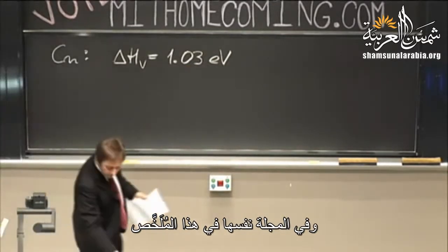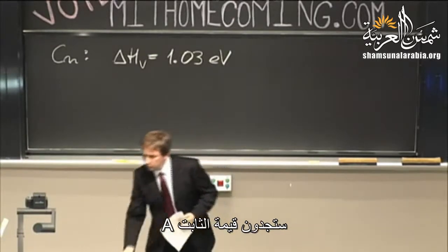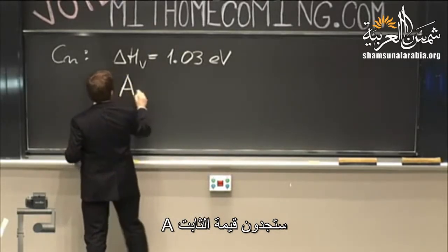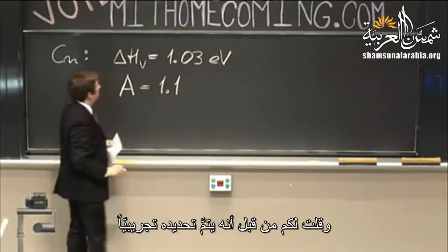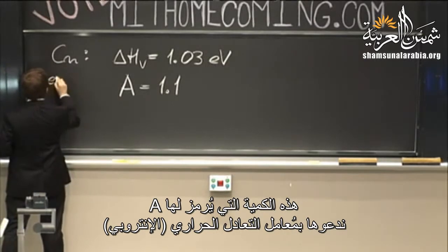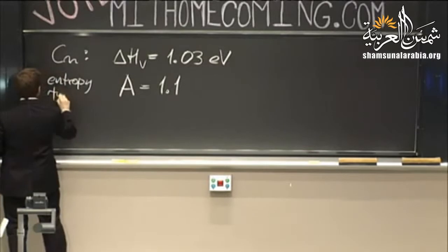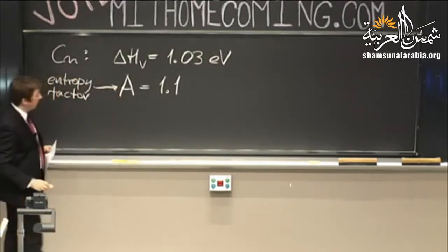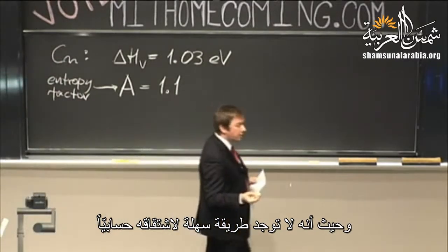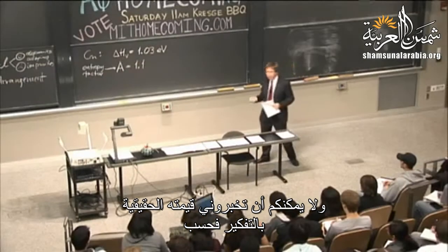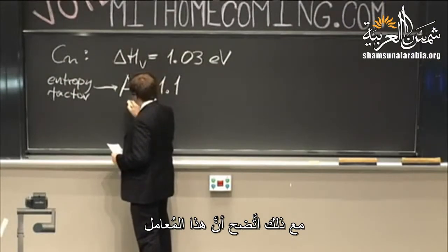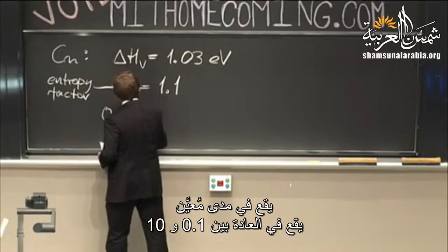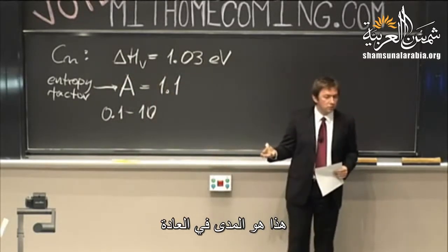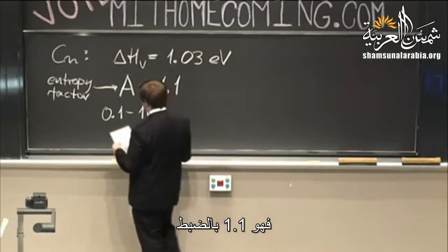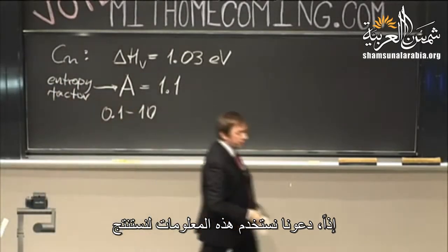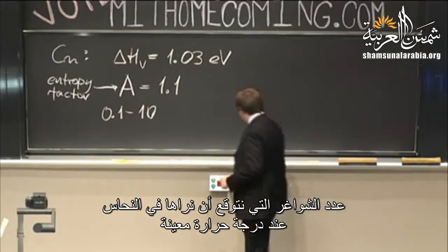Furthermore, in the same journal, in the abstract there, you'll find the magnitude of this constant A, which, as I told you, is experimentally determined. This quantity A we call the entropy factor. And even though there's no way to very easily derive it, I can't tell you what the entropy factor for iron is, and you can't really tell me just by thinking about it. Nevertheless, it turns out that this factor usually falls within a certain range, between 0.1 and 10. That's usually the range in which you find A's. And in the case of copper, it's very much in that range, it's just 1.1. So let's use this information to actually figure out how many vacancies we expect to see in copper at a given temperature.